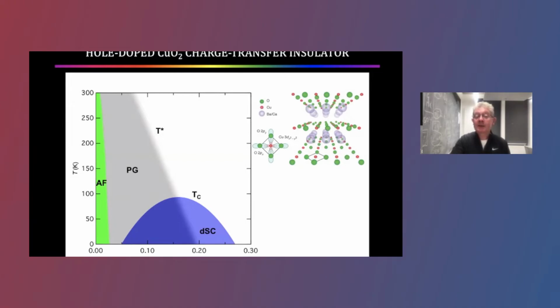So p is the number of hole densities per CuO2 unit cell. Temperature on the left-hand axis. You only have to put 1 or 2% of holes into this compound to destroy the antiferromagnetism. A mysterious phase, which I call electronic dark matter, but other people call the pseudogap, appears. And then by the time you get to 15 or 20% hole density, you get high temperature superconductivity. It's beautiful, but we don't know why. What is the actual mechanism that's producing this robust high temperature superconductivity in dozens of different compounds? It's quite a universal phenomenon.